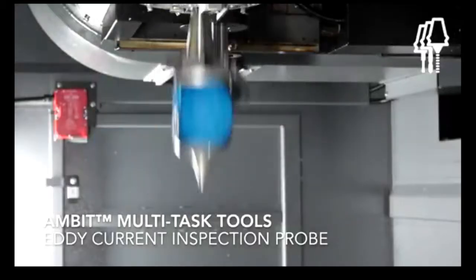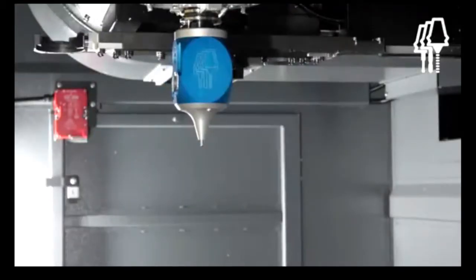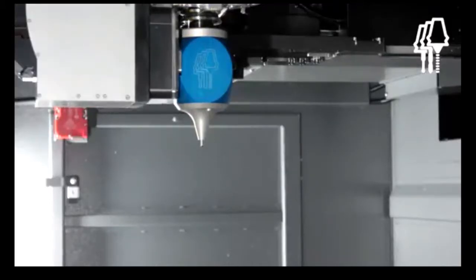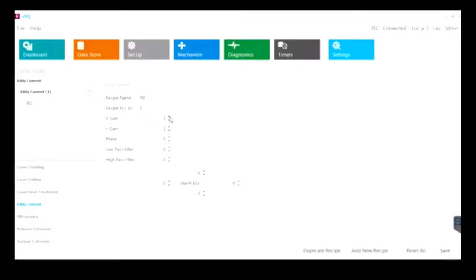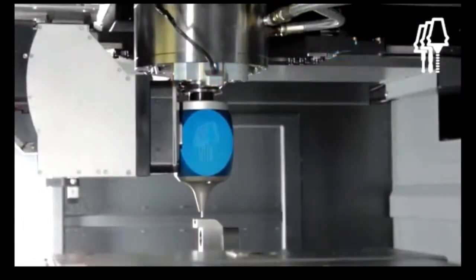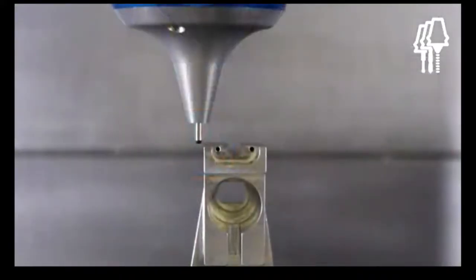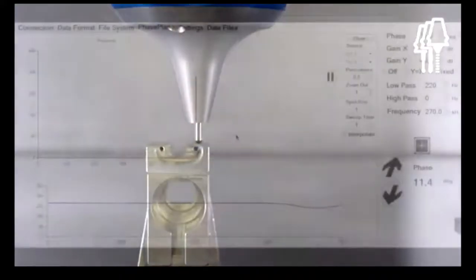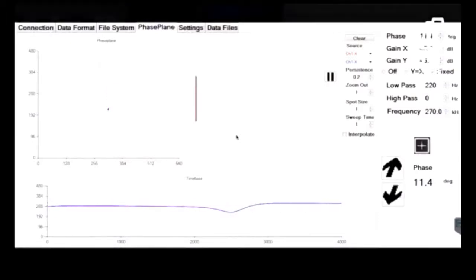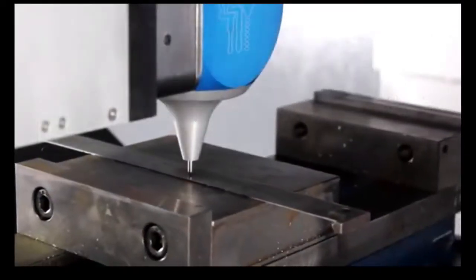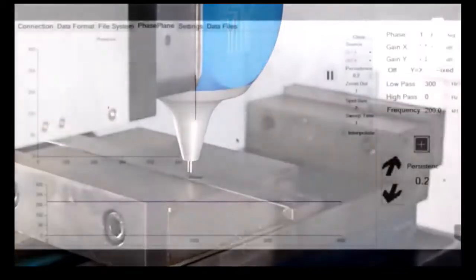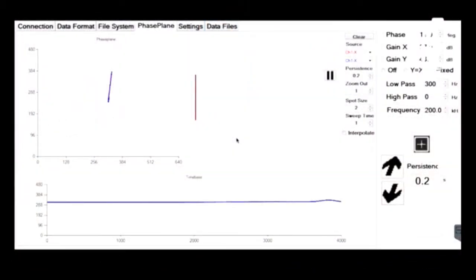So in it comes, again, on a tool holder. Once it's in the spindle, drop down, you need a little connection to supply the electrical. Set up whatever parameters you want to be probing at. And now you can look at not only surface, but subsurface. Right? The penetration on this is about a layer thickness of what you've just deposited. You can look for voids. You can see cracks. You can see microscopic cracks. Suddenly you have sensitivity in areas that has not been possible, at least not in process on the machine.